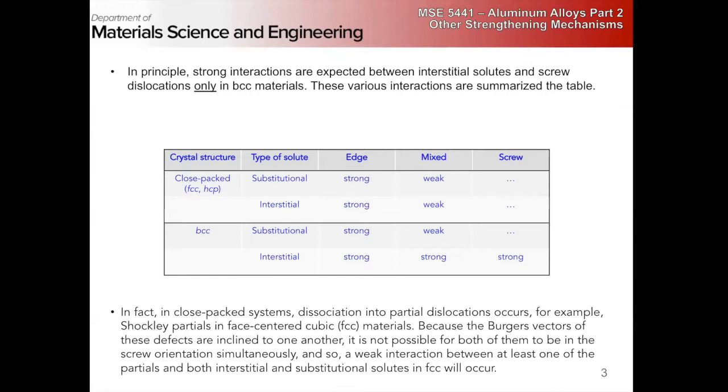In aluminum, where our stacking fault energy is high, our partials are not very far apart from each other, right? So they can still come together to be pure screw parts to cross slip.